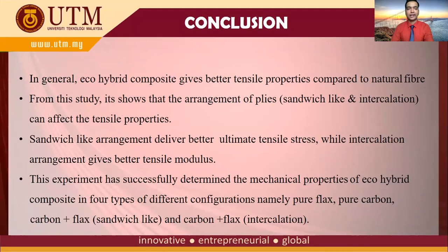As for the conclusion, in general, eco-hybrid composite gives better tensile properties compared to natural fiber. From this study, it shows that the arrangement of plies, sandwich-like and intercalation, can affect the tensile properties. Sandwich-like arrangement delivers better ultimate tensile stress, while intercalation arrangement gives better tensile modulus. This experiment has successfully determined the mechanical properties of eco-hybrid composite in 4 types of different configurations, namely pure flax, pure carbon, carbon plus flax sandwich-like, and carbon plus flax intercalation.